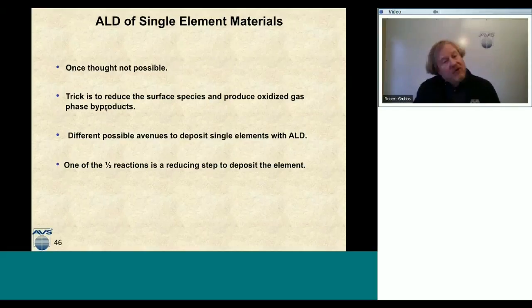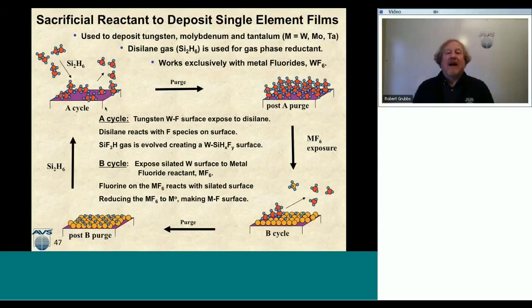The first one I'd like to talk about is using a sacrificial reactant to deposit the single element. This is used to deposit tungsten, molybdenum, and tantalum metals. It uses disilane gas as the reductant gas, and it works exclusively with metal fluorides, tungsten hexafluoride, molybdenum hexafluoride, and so on. Here's how this chemistry works. I have a surface and I come down with disilane, and it'll form maybe a multilayer. There's probably some fluorine on the surface, I'll give you that as an assumption. And I'll make this fluorodisilane species on the surface. This is going to be the reducing surface, and I put that reducing surface down first.